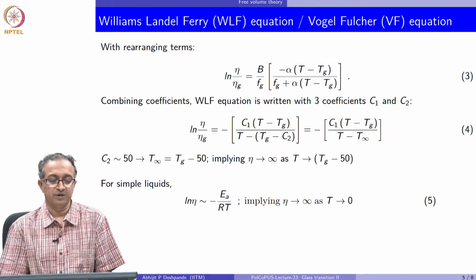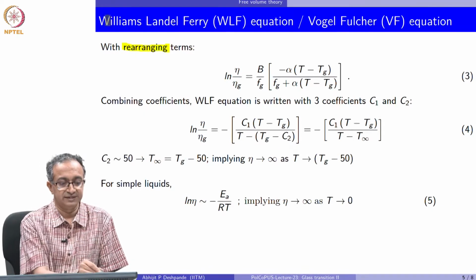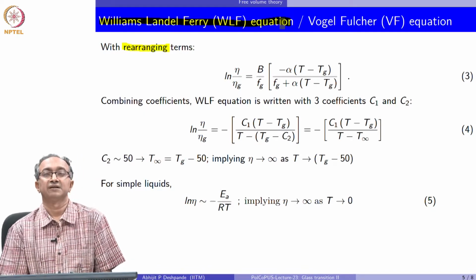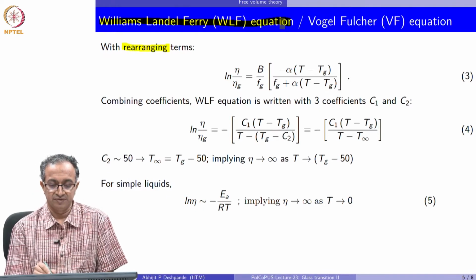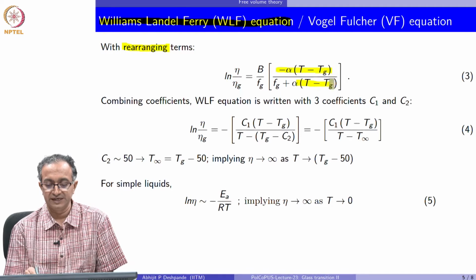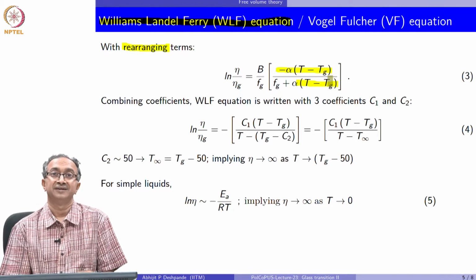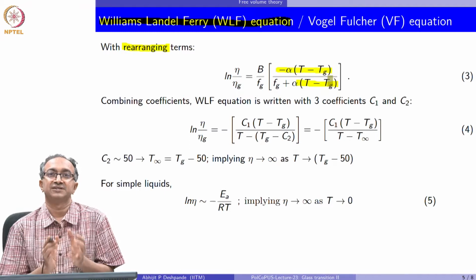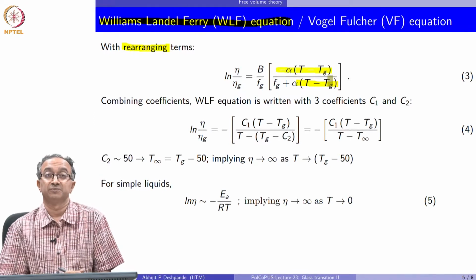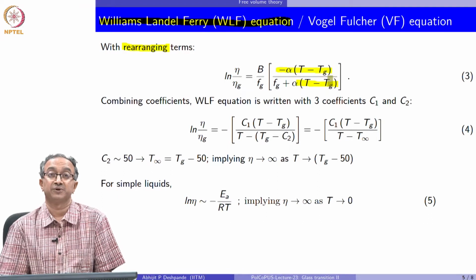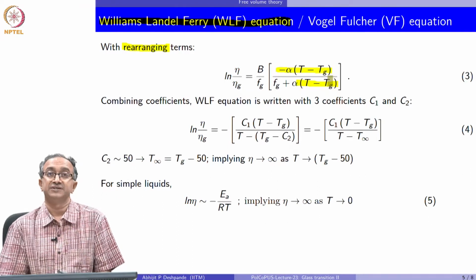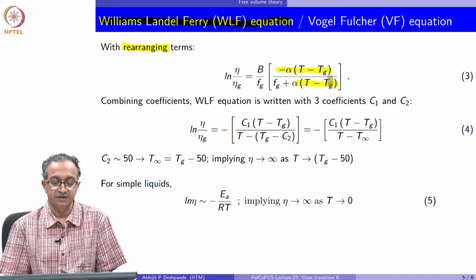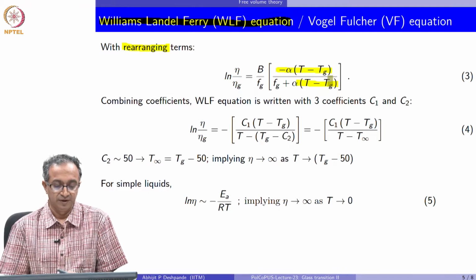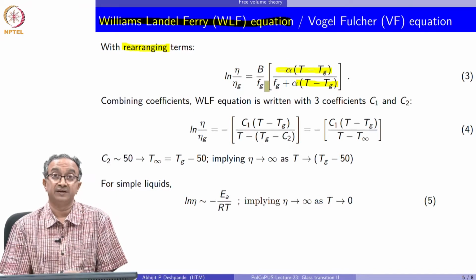So, if you do a little bit of algebra and arranging of terms, we get what is called the Williams-Landel-Ferry equation, and when you do rearrangement, you are basically getting a factor T minus Tg, and this is the factor that I talked about when I described glass transition as a cooperative process, segmental relaxation as a cooperative process, where the temperature difference from the glass transition with respect to glass transition is the key feature as opposed to the activation energy.